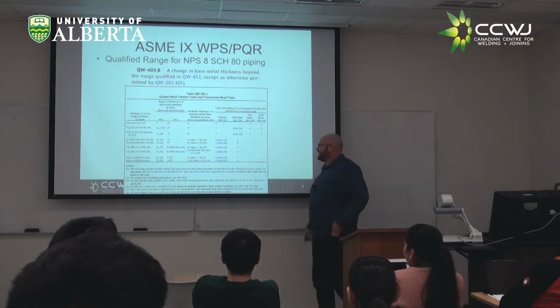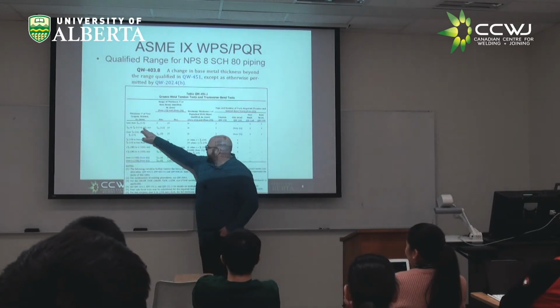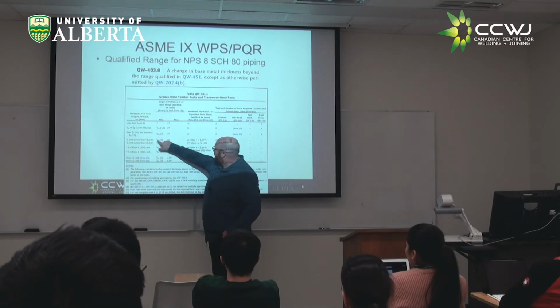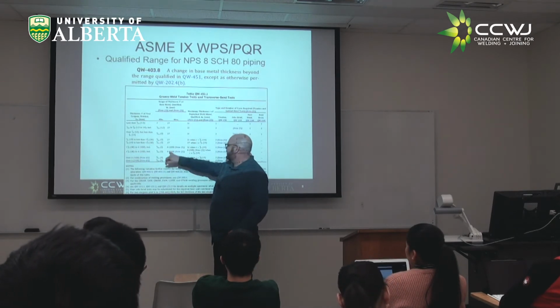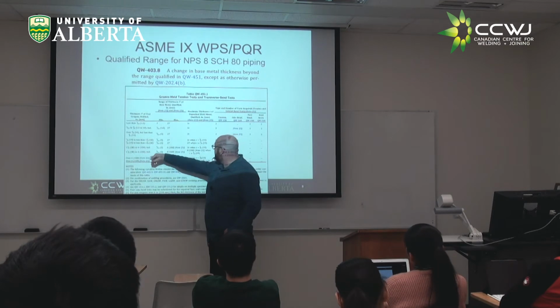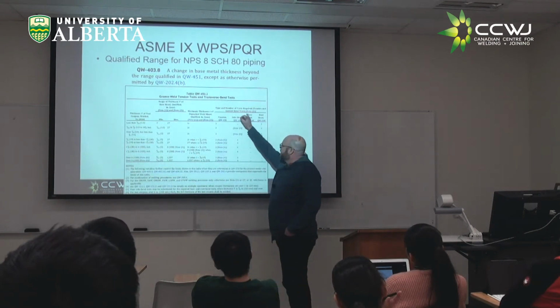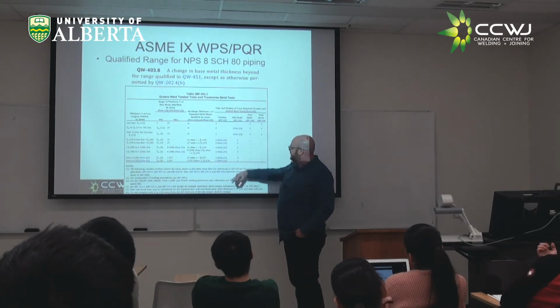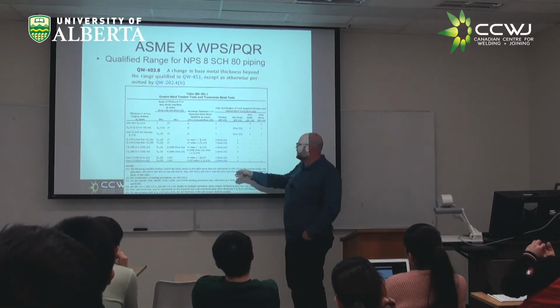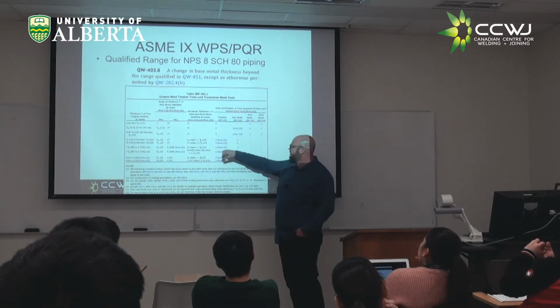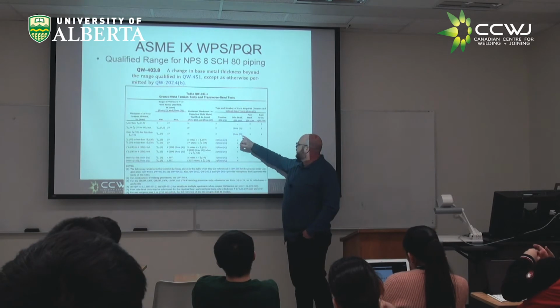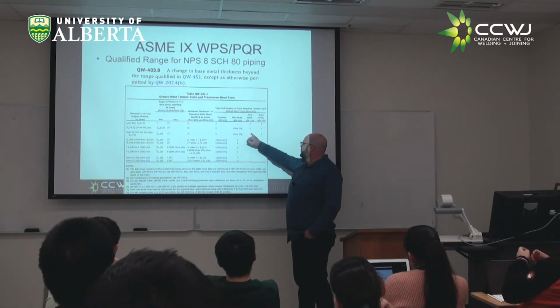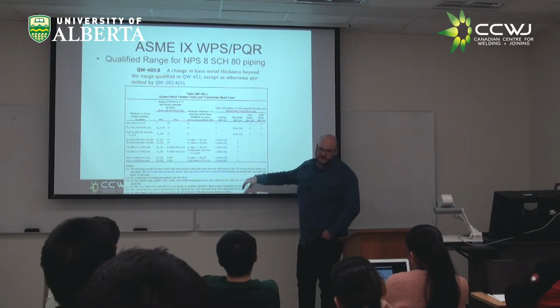So, anyway, we can see here you can select your coupon thickness. It gives you your minimum qualified thickness and your maximum qualified thickness, which in this case is 2 times your coupon thickness. This table also defines a lot of the tests you need to do for almost everything, with the exception of special processes. It's 2 tensiles, 2 face bends, 2 root bends, or 4 side bends.